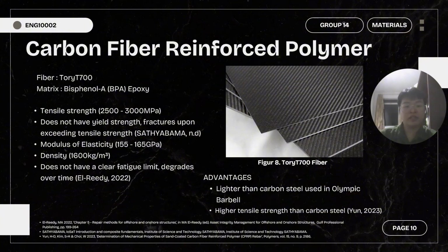Its modulus of elasticity ranges from 155 to 165 gigapascals. The density is about 1,600 kilograms per cubic meter, which is far lighter than the steel normally used for Olympic barbells, which is around 7,800 kilograms per cubic meter. In terms of fatigue strength, the material does not have a clear fatigue limit. It slowly degrades over many cycles, although this can take millions or billions of cycles. The main advantages are that the material is much lighter than steel and it offers a higher specific strength.